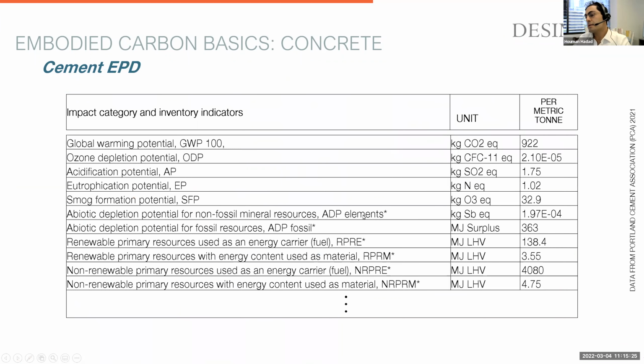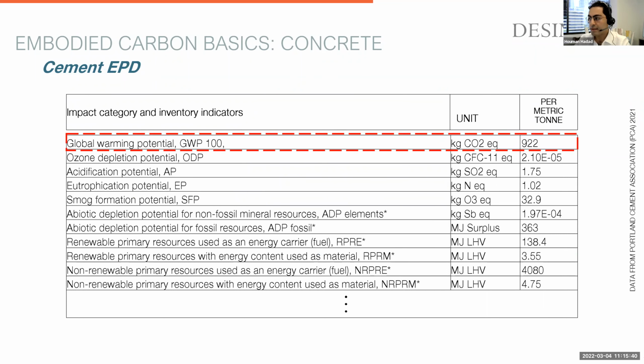So then let's talk about the numbers for cement. What you're seeing here is called an EPD. EPD is almost like a nutrition fact, they call it the nutrition fact for materials these days, of anything that you buy in the store. Like the nutrition facts, you probably are most interested in the number of calories that you're consuming, right? In that case, it becomes global warming potential, or how much carbon dioxide is released into the atmosphere as a result of creating 1 tonne of that material. So for cement right now, the number is 922 kilograms of CO2 for every ton of cement that is produced. So it's a number close to, again, steel that we saw before.